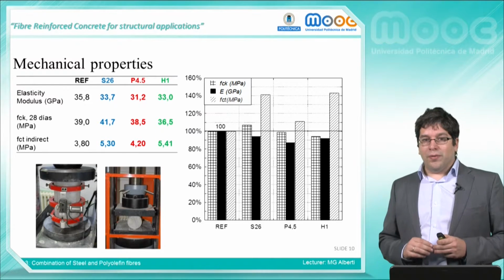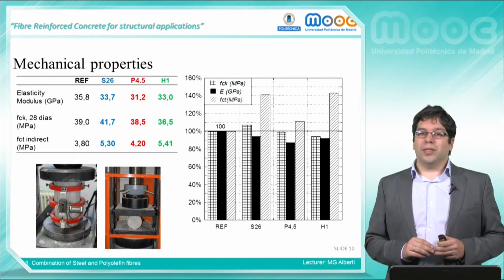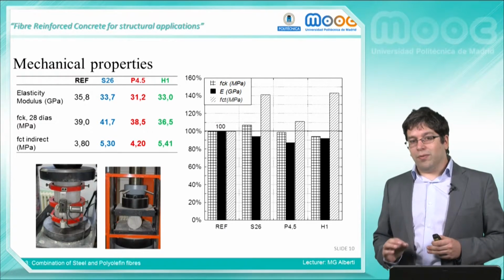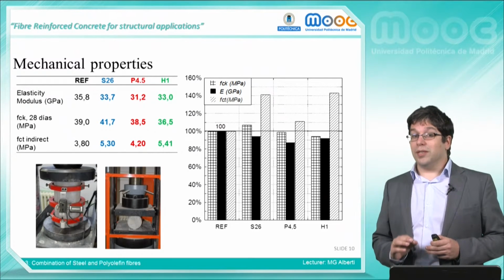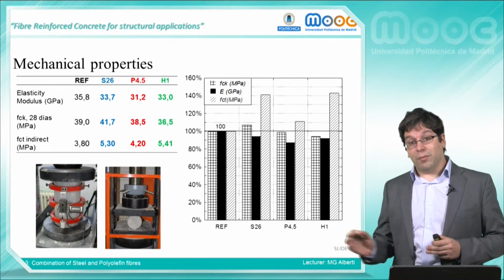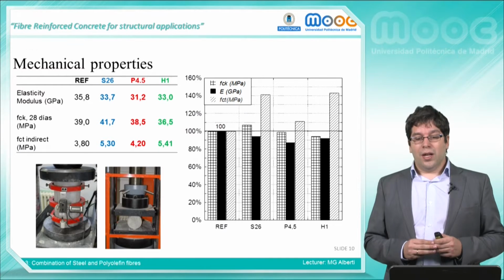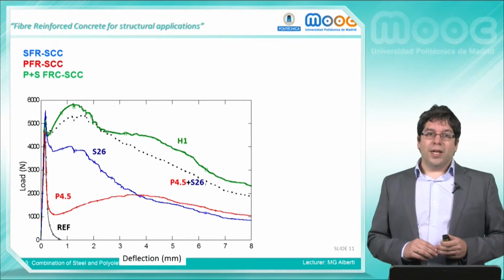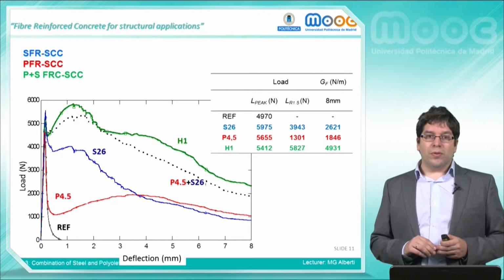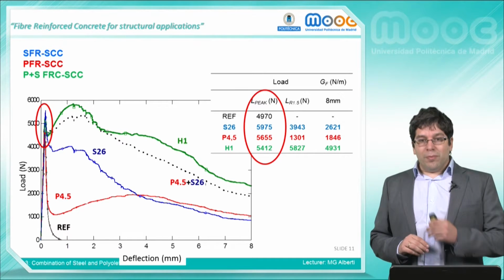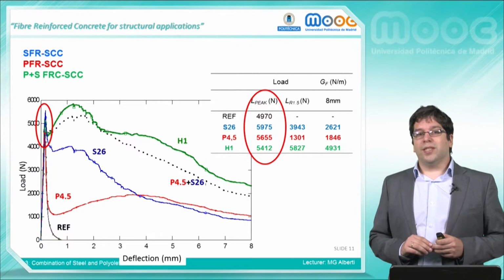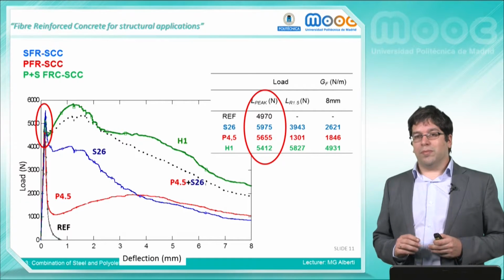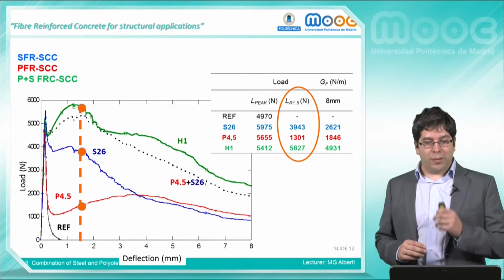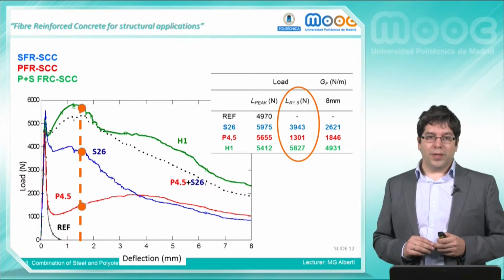As expected, few changes appeared in mechanical properties. Just note that steel fibers are able to increase splitting tensile strength and polyolefin fibers not. Concerning fracture curves, the peak load was close for all the formulations, and the hybrid fiber-reinforced concrete reached its maximum even higher than the limit of proportionality for deflections of about 1.5 mm.